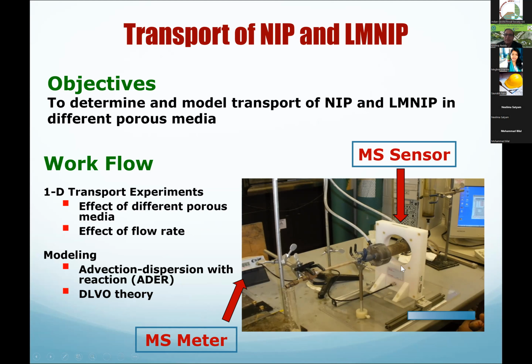So basically what we do is we flush this, and this magnetic susceptibility sensor is on the track. You see the track here? We move the sensor from one end to the other and take the readings of magnetic susceptibility, and that is correlated to the iron content. In the beginning, you can see the iron is coming, you will see the readings detected. And as the iron moves, you can measure the MS values depending upon how much it's moving. Based on that, you can look at the dynamic transport of the iron, how it is transporting with time.